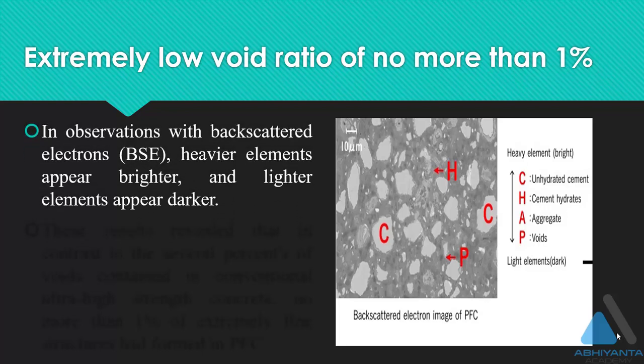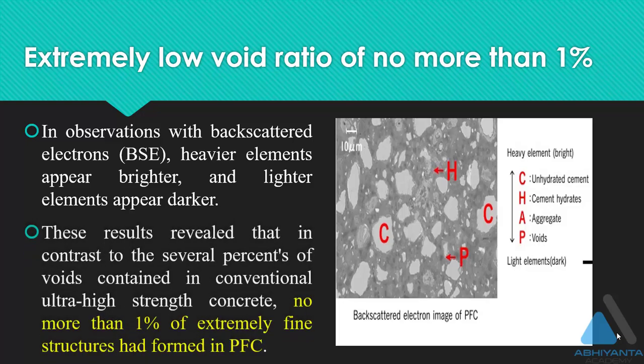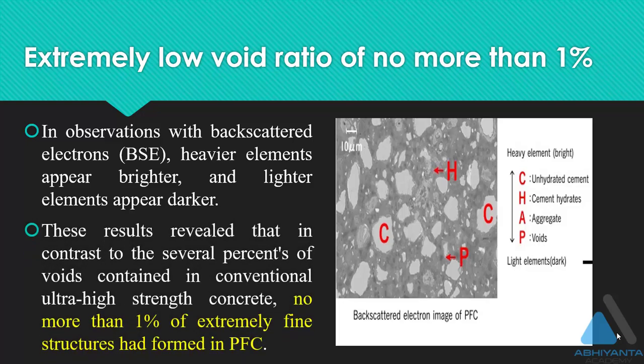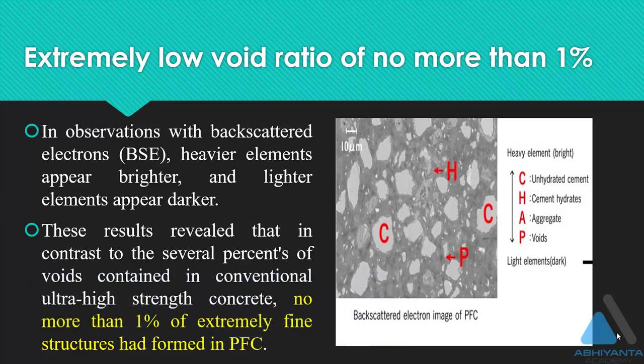This is a backscattered electron image. On the right hand side, you can see that heavier elements appear brighter and lighter elements appear darker. These results reveal that in contrast to the several percent of voids contained in conventional ultra high strength concrete, no more than 1% of extremely fine voids were present in PFC. Here C pertains to unhydrated cement and P pertains to voids. You can see that there is a very small amount of voids in the concrete. But we have to verify it with the strength.